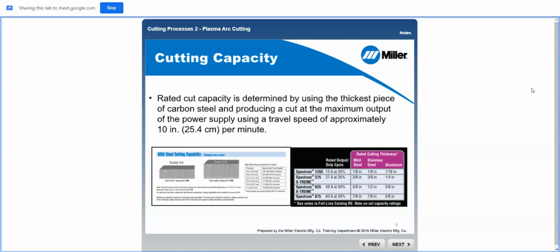Rated cutting capacities for aluminum will be much less than shown the rated thickness due to aluminum's high thermal conductivity. So if we have 1/2 inch thick aluminum, we will not be able to cut it at the same settings as we do for the 1/2 inch carbon steel. The reason for that being is since aluminum is so highly thermoconductive, meaning that it absorbs heat very quickly, the material doesn't get hot enough or stay hot enough for us to cut at the same pace as we would for carbon steel, because carbon steel tends to stay hot as we cut it.